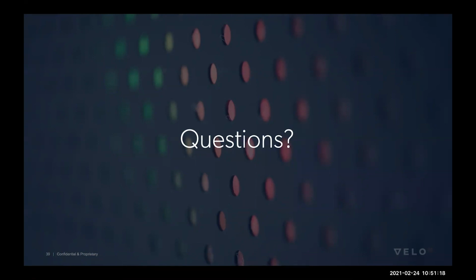And this is more for Jim and Jose. Have you considered other materials like Hastelloy, for example? Yes, short answer is yes. Inconel 718 is particularly amenable for the supercritical CO2 application. It behaves very well under the high temperature corrosive environment, and therefore we did not have to deviate much from what we would have normally used.